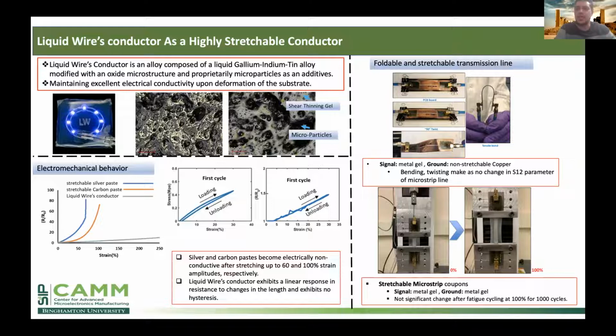In collaboration with Liquid Wire, we developed a metal gel that is a highly stretchable liquid metal. When you say liquid metal, most people think about mercury, but this one is a gallium indium tin eutectic alloy. Unlike mercury, which is toxic, this one is not toxic and has a low vapor pressure. By adding some proprietary additives, and also the gallium oxide that naturally forms once it's exposed to the air, we modify the rheology so that it can be stencil printed. Stencil printing is a fast and established process, so it can scale to manufacturing.